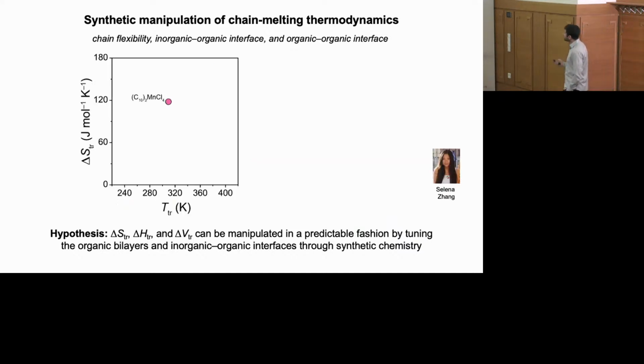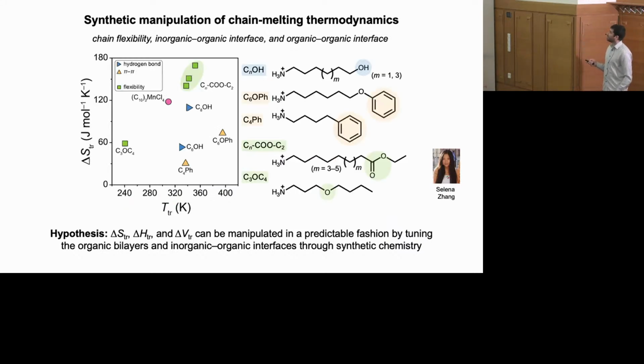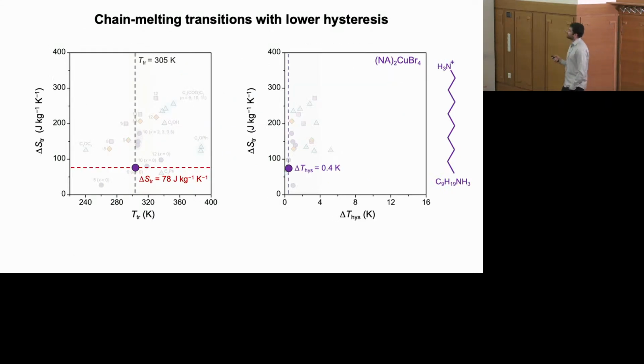And so an undergraduate researcher in my group, Selena, has explored a really wide range of different kinds of functional groups that can be present in the organic bilayers of these materials, and started establishing relationships between phase change thermodynamics in these different kinds of structures. And so I'll just highlight one example of a particularly interesting compound that she found, which has the exact same structure as the manganese 2D perovskite I was talking about previously, but now we have copper and bromide atoms in the inorganic lattice and a C9 rather than C10 chain.